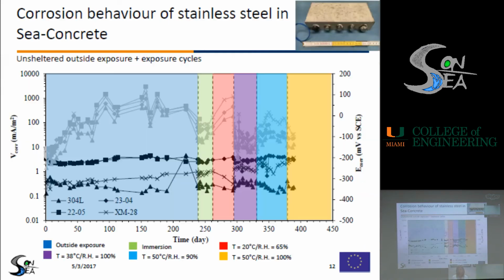This figure shows as an example the corrosion behavior of the 4 types of stainless steel embedded in the sea concrete and exposed outside unsheltered and then to the different exposure cycles. We can observe that the corrosion potential of the stainless steel was quite high even in the most aggressive exposure condition, and the corrosion rate was low, indicating that all the stainless steel maintained the passive condition even in the harshest environment.